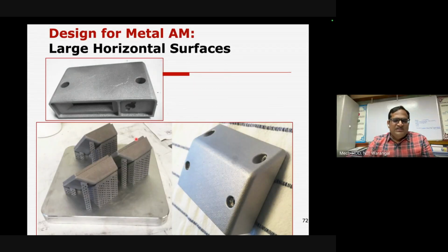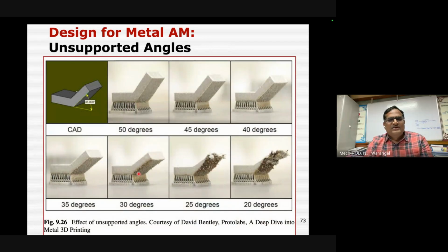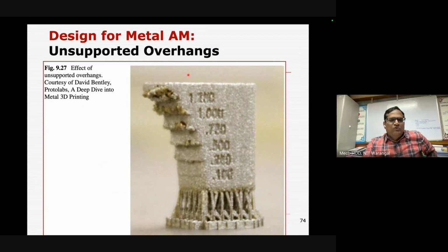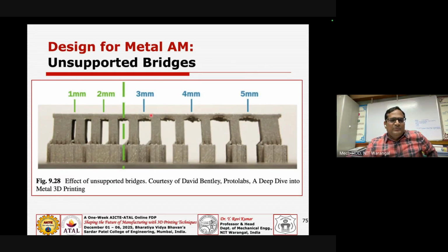And large horizontal surfaces, always try to minimize that kind of stuff. As I already mentioned, the overhang angle dictates a lot in terms of your supports. Also we need to understand these overhangs, what is the minimum overhang angle or thickness. And these bridges, what could be the bridge? Maybe 1 mm, 2 mm, it's fine, but 3, 4, 5. Then we need to adopt design guidelines in order to realize all these features very well. Otherwise, you may end up with a bad component.